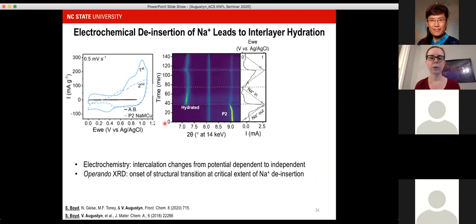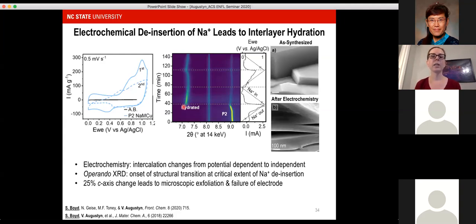What we obtained from the operando X-ray diffraction is that this is the first sodium deinsertion cycle of the P2 phase. There is a very discrete stage upon the deinsertion of sodium ions where the structure transitions from the P2 phase to a hydrated phase that we called birnessite-like, meaning that water molecules were now present in the interlayer. And then this birnessite-like, hydrated interlayer phase was electrochemically active on subsequent cycles. It would cycle sodium ions in and out, with contraction of the interlayer during sodium insertion and expansion during deinsertion. However, during this transition, there's a 25% c-axis change that leads to very significant microscopic exfoliation and essentially failure of the electrode.